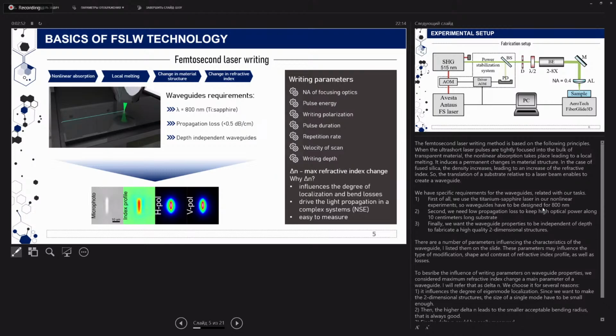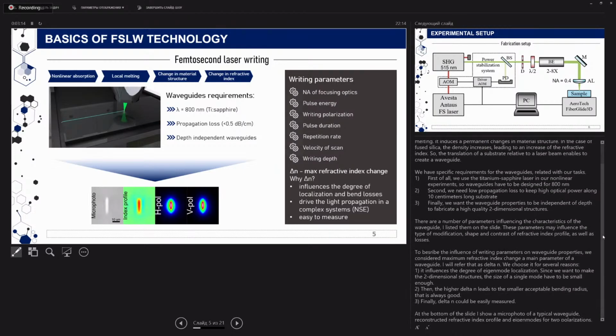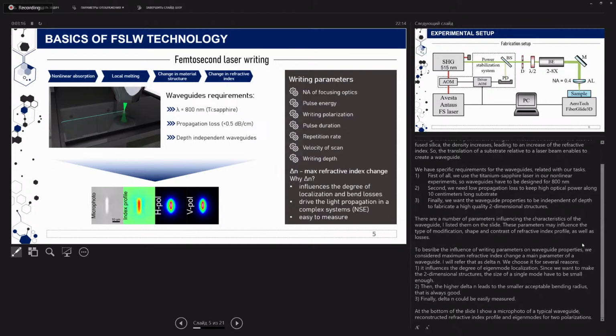We have specific requirements for the waveguides related with our tasks. First of all, we use a titanium sapphire laser in our nonlinear experiments, so waveguides have to be designed for 800 nanometers. Second, we need low propagation loss to keep high optical power along a 10 centimeters long substrate. And finally, we want the waveguide property to be independent of depth to fabricate high quality two-dimensional structures.